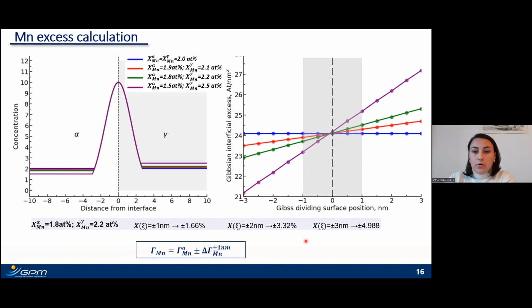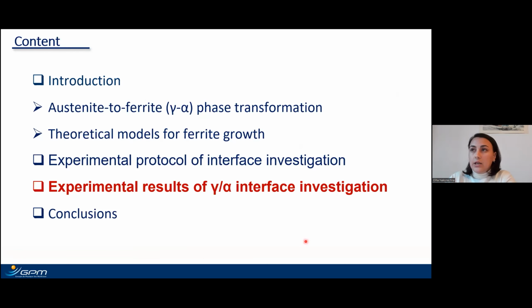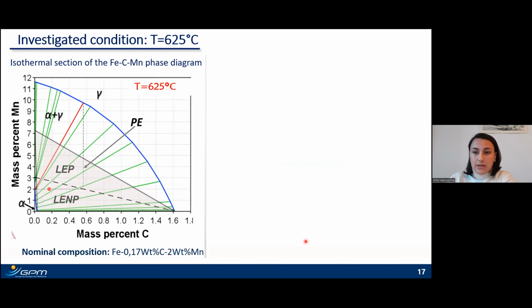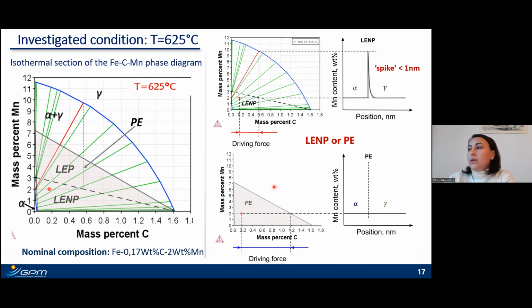And now I would like to show you some APT results in the case of a transformation temperature of 625 degrees Celsius. If you look at the isothermal phase diagram at this temperature for the alloy with the investigated nominal composition, shown here as a red point, we expect that LENP or para-equilibrium is operating at this temperature. Just to remind you, in the case of LENP, we expect a manganese spike less than 1 nanometer in width, and in the case of para-equilibrium, the manganese profile is expected to be flat.